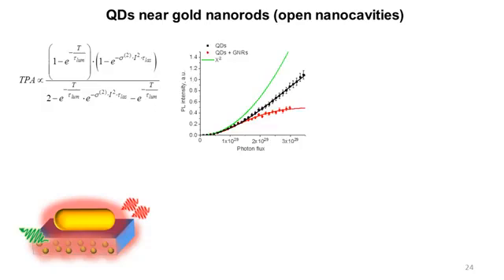In the experiment, we measured the dependence of the photoluminescence intensity on the excitation intensity for two samples: first quantum dots in the polymer matrix, black squares on the graph, and quantum dots in polymer matrix covered with gold nanorods, red circles on the graph. We fitted these dependencies using the presented equation and found that the highlighted part of the equation was different for these two samples. Assuming that the radiative lifetime was the same in both cases, the change is related either to the change in the excitation intensity or to the absorption cross-section. If we use only the far-field excitation intensity, then we need to use the changed effective two-photon absorption cross-section, which change reflects the change in the position of the inflection of the saturation dependence.